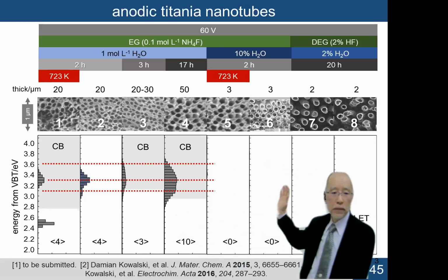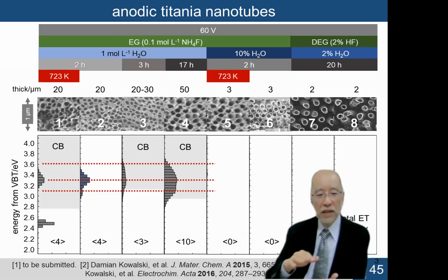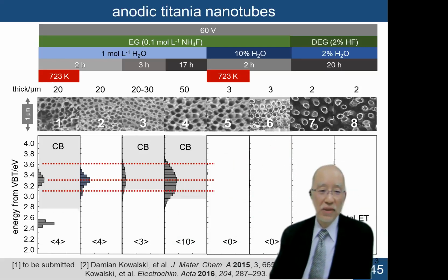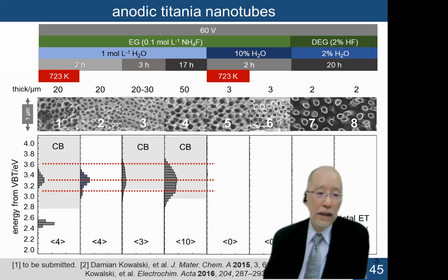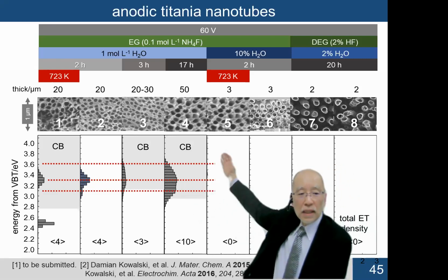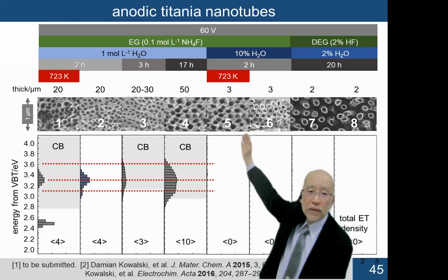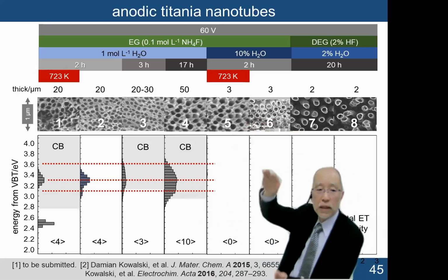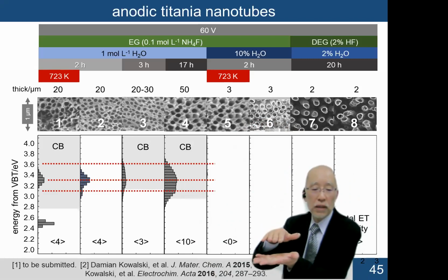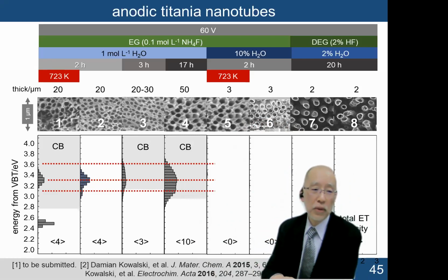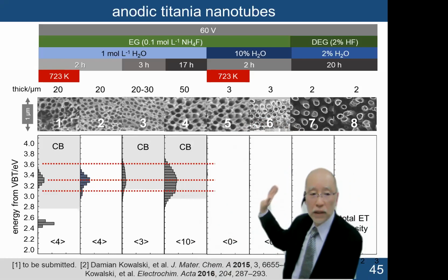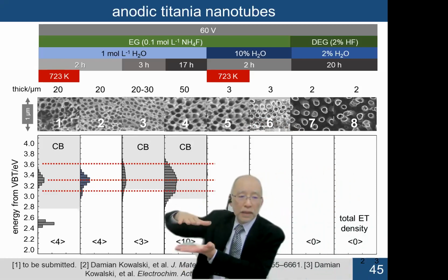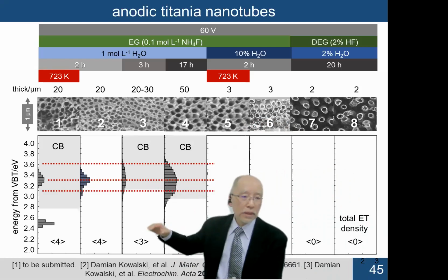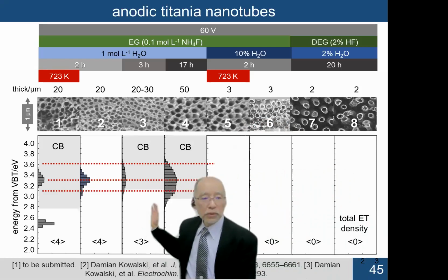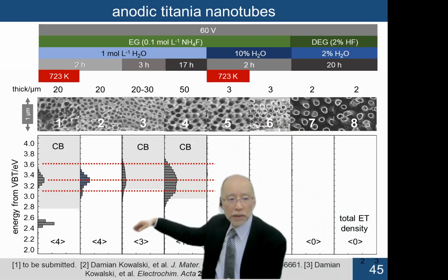For a thin film, that is 3 micrometers. A 3 micrometer film is, in the ordinary sense, not thin; it is a thick film. But the density is very, very low. So even if it is 3 or 2 micrometers thick, the actual weight of titanium is very, very low, so it is impossible to see any XRD pattern. But if the thickness is high enough, it is possible to see those XRD patterns.